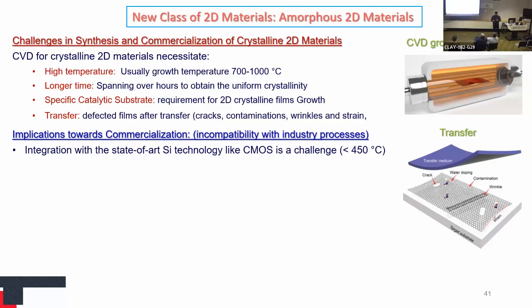And also in the end, because all the growth is happening on the copper, we have to ultimately transfer to the required substrate, for example, membranes, silicon oxide or other substrates. And that transfer will generate a lot of defects. Also in terms of processing, this temperature is very high compared to CMOS processes, which are mostly below 450 degrees Celsius. So making crystalline material is always at the expense of high temperature. It's a big challenge to translate into the industry.